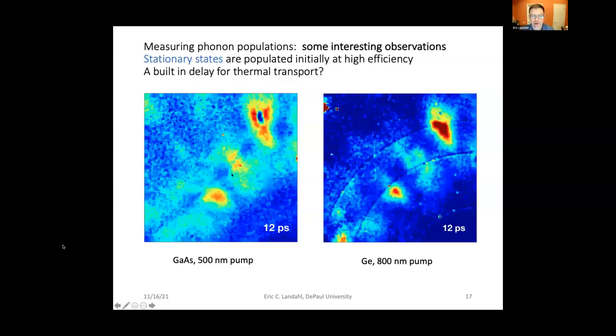One is the large quantity of intensity that is shown here in between zones, which we believe is unobserved. We'll talk about David Reis's group's measurement in bismuth in a moment, but they show different locations lighting up. The zone edge is interesting because, of course, there's no group velocity in the dispersion curve for these phonons. They're stationary states, and they're populated at amazingly high efficiencies. Even when you take into account the different selection rules for polarizations of scattering, this is really, in this difference map, a very large amount of phonon flux comparable to what's at zone center, even at moderate, non-damaging fluences.